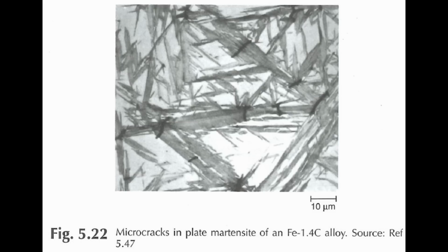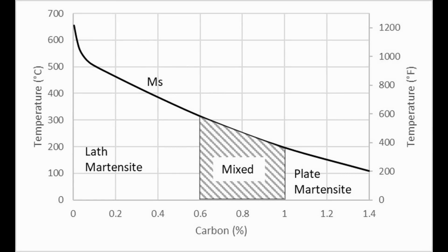So plate martensite is often undesirable because the toughness is significantly lower, even at the same hardness. So if you tempered plate martensite down to the same hardness as lath martensite, the toughness of the plate martensite would still be lower. And so 1095 has 0.95% carbon, so it's right at that point where it can be almost all plate martensite if you austenitize it hot enough to dissolve all of the carbide and have all of that carbon in solution. But even with normal austenitizing temperatures, there can also be significant amounts of plate martensite in 1095, which reduces its toughness. Bainite does not have this issue. There is no plate Bainite. And so you can avoid that plate martensite issue, and that is one of the big reasons.